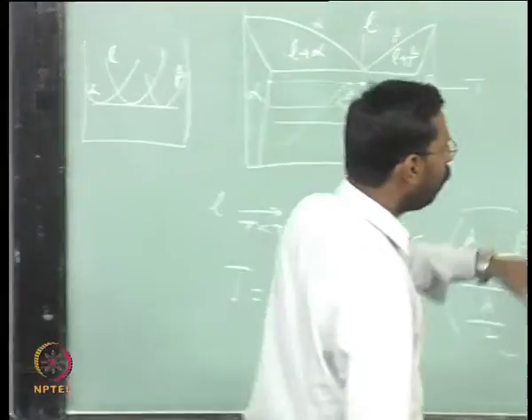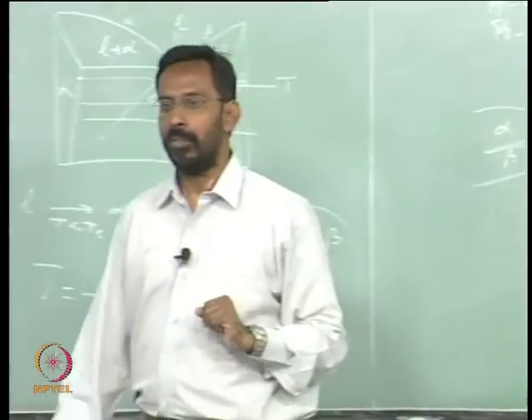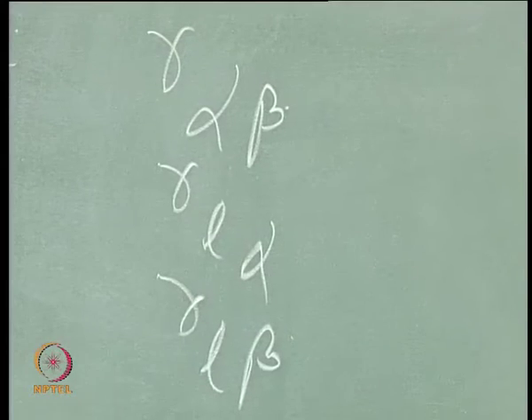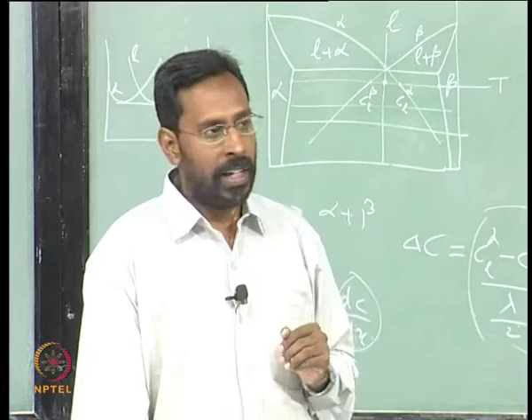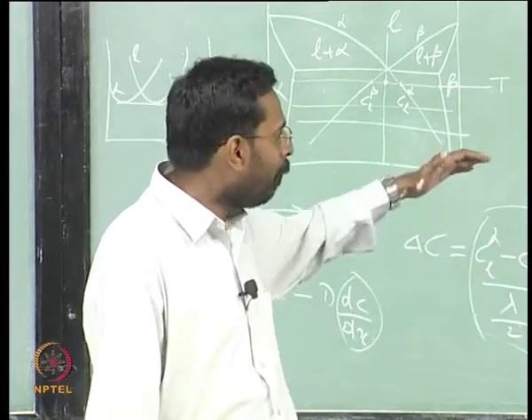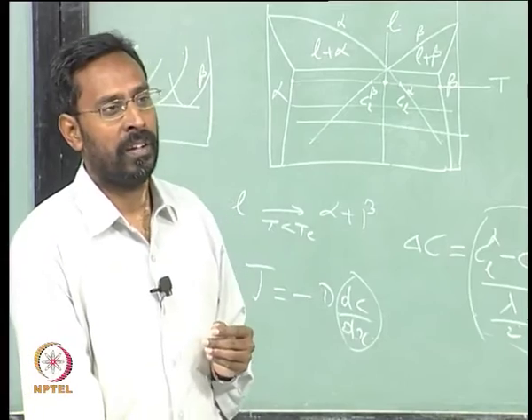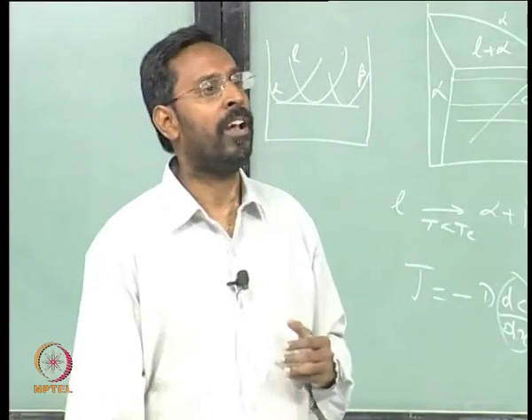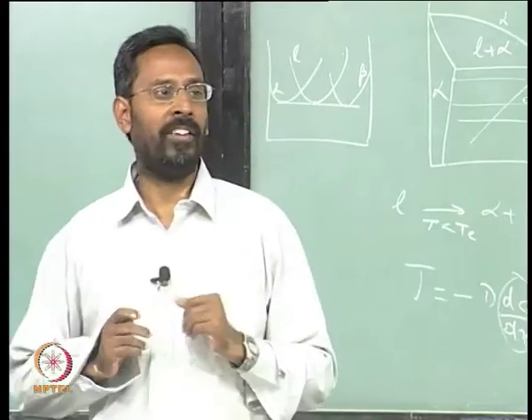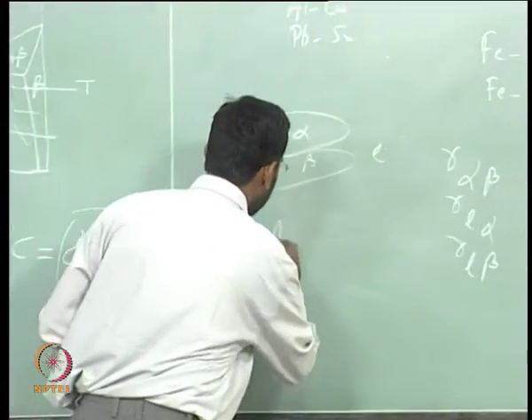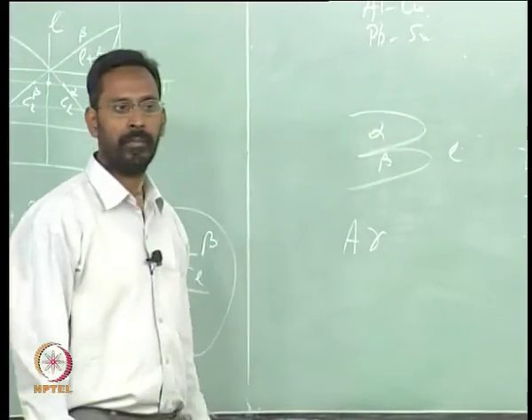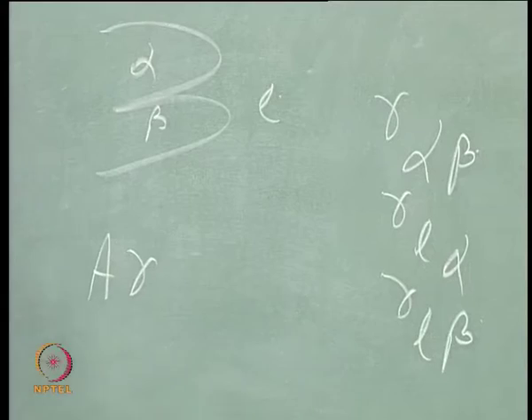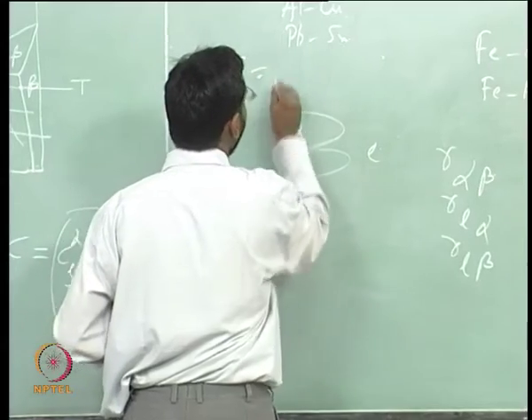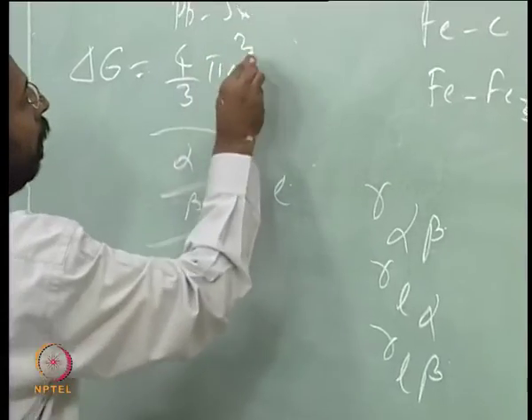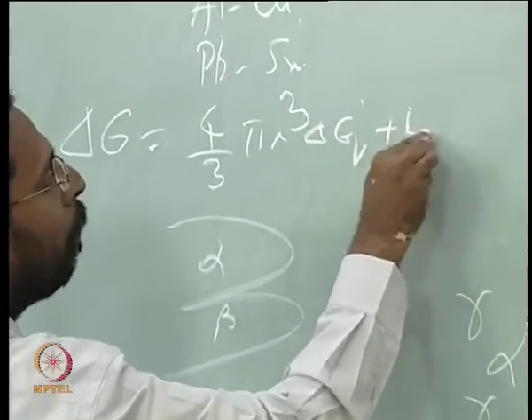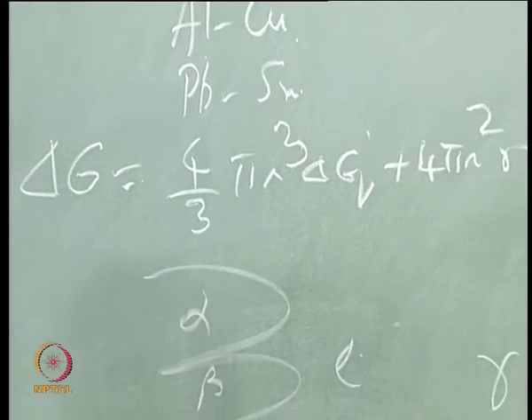So whenever you have this kind of 3 interfaces, the system would choose the one which has the lowest interfacial energy. If a particular system has alpha beta interfacial energy as the lowest, the system would like to have that particular interface maximized, so that the overall interfacial energy - A into gamma - is minimized. This is what is actually preventing the transformation. That is why, if you remember delta G, we always write 4/3 pi r cube delta GV plus 4 pi r square gamma.